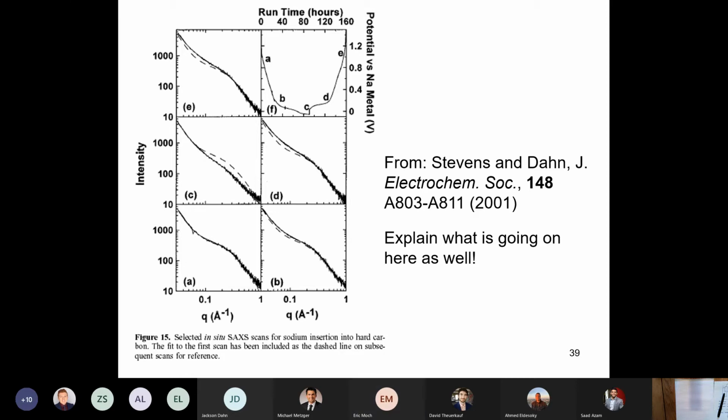If you did reduce the porosity, I think you'd reduce the capacity in this lower voltage plateau as well, which is not what you want to do. Right. Yeah, you're sort of trapped in a box with these carbons because this nanoporosity is good for storing the alkali metals, but it increases the volume of the material a lot. So volumetrically, they're not that great.